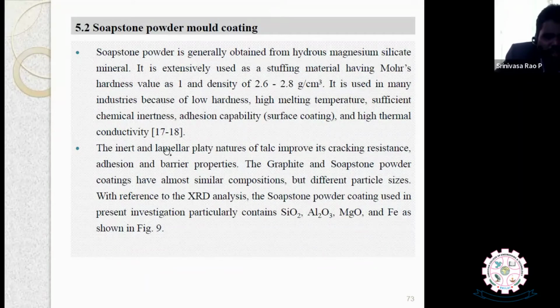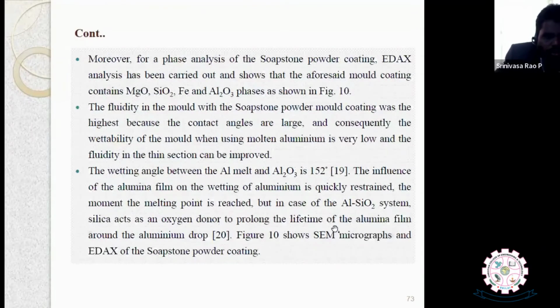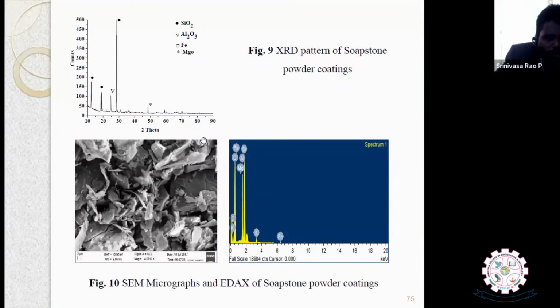And it improves the cracking resistance, adhesion and barrier properties. So the graphite and soapstone powders have almost similar composition but different particle size. With reference to the XRD analysis, the soapstone powder coating used in the present investigation contains silicon oxide, aluminum oxide, magnesium oxide, and Fe. Okay. And then we have carried out the SEM and EDAX analysis for soapstone powder also. This is what we have obtained.